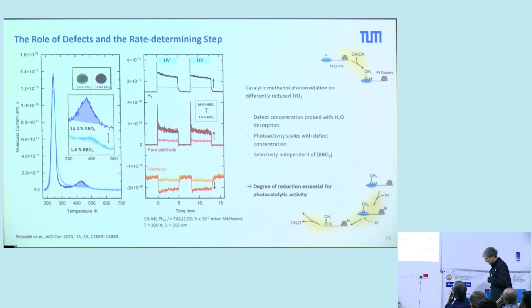Now let's have a closer look. We have seen that these BBO sites are important. And so you can tune these BBO sites on our titanium single crystal. So you can produce single crystals with a high number of BBO sites and a low number. And this you can titrate by water. And you see here two surfaces, a different amount of BBO sites. We estimated about 14% and here about 1.6%.